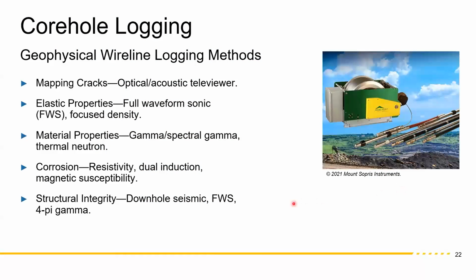And you get, of course, the cores coming back. So again, I'm going to use what's known as borehole logging, or what we call core hole logging technology. I'm going to use basically optical televiewers and acoustic televiewers. I'm going to show some examples of mapping cracks from the core holes, and looking at elastic properties using sonic and density tools, which is similar to the drilled shaft environment that Bernie showed with the cross-hole sonic and 4-pi density. These are other logs, which I don't have time to show examples of right now, but we look extensively at this whole idea of borehole logging.